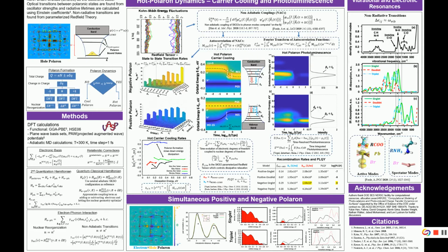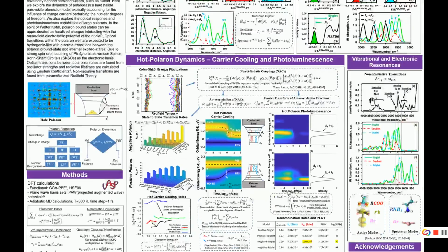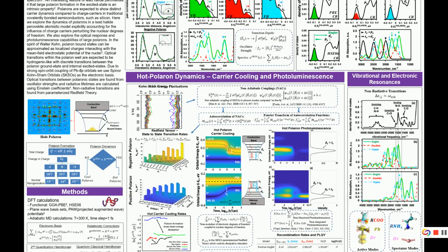So it's not very good at emission, but we did notice an interesting feature: between all of the models that we investigated, there was a range of different photoluminescence quantum yields. Looking into the data more, we see that for all the models the radiative rates are roughly the same, differing by maybe half an order of magnitude, while the non-radiative rate for our most efficient emitter showed a two orders of magnitude reduced recombination rate. To see if there's a possible mechanism for this trend, we decided to hunt for resonances between vibrational modes of the system and transition energies from the system.